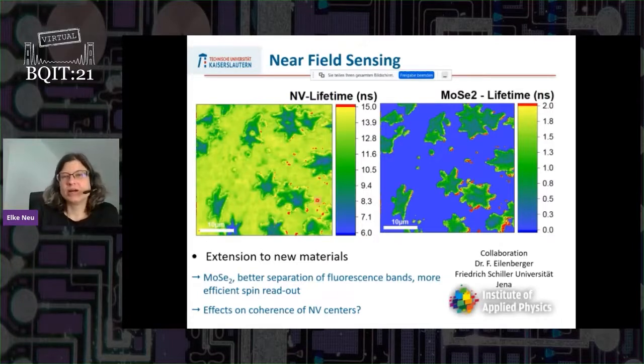We have now new samples with molybdenum diselenide flakes. They form these little stars here. Again, we see the reduction of the lifetime, as you can see here, now in the darker areas. And we have now better samples where we can also clearly distinguish between the NV and the molybdenum diselenide fluorescence.